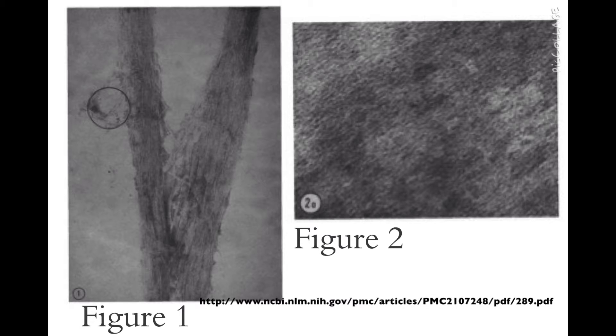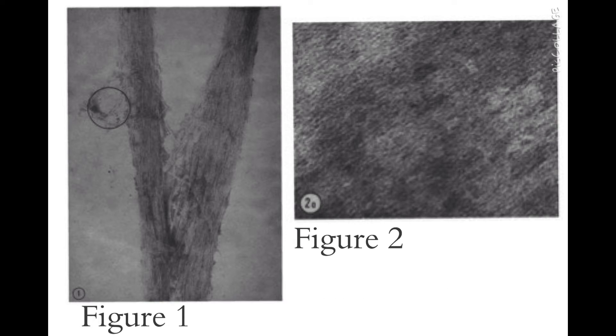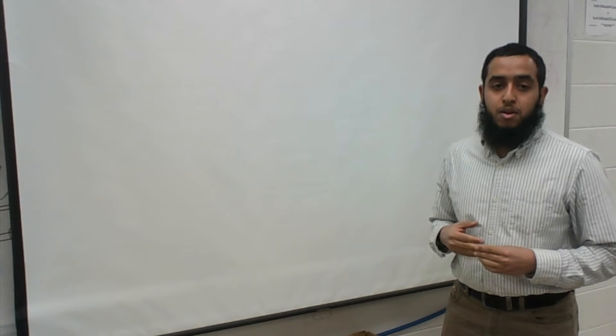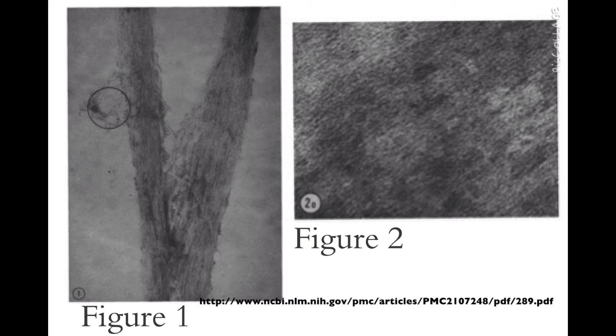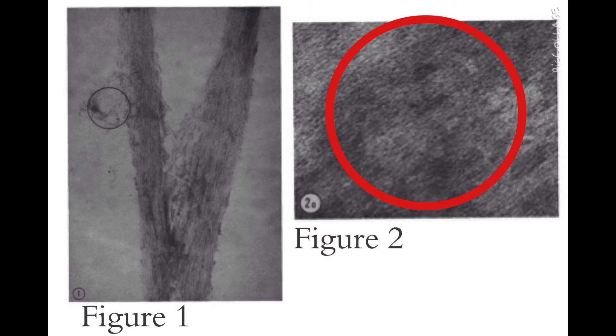These figures suggested that silk fibroin has ribbon-like filaments of well-defined lateral dimensions, which can also be called micro-fibrils. In most instances, the methods of preparation or examination would have prevented the recognition of the highly asymmetric cross-sectional shape in these micro-fibrils. The asymmetric shape is confirmed by the cross-section in that figure, where the dimensions of the unstained areas agree with those assumed in this figure.